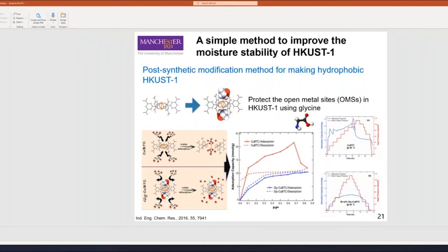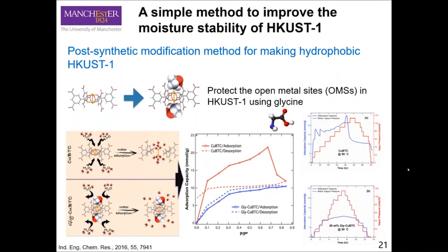Which one is this one you're mentioning? Page 21. They ask, yeah, for the copper MOF before it's coated. Before coated, right? Yeah. Before coating, the mass drop is due to the collapse of the framework during the water vapor adsorption at high temperature. So as you can see, at high temperature the MOF can be damaged significantly.